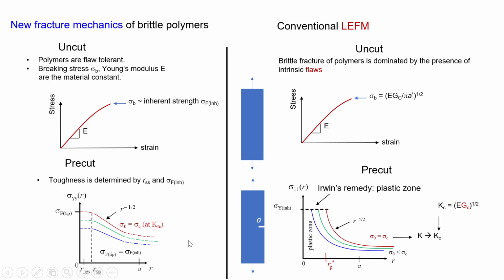Not only is there the emergence of a stress plateau, but this plateau occurs even at low load. Not only is there this plateau, but this plateau has nothing to do with yielding and plasticity. It perhaps has to do with the tip being blunted. In other words, when you make a pre-cut to do the Gc experiment, your scissors or your blade make a cut, the material just naturally responds, and that determines this value, which can vary slightly.